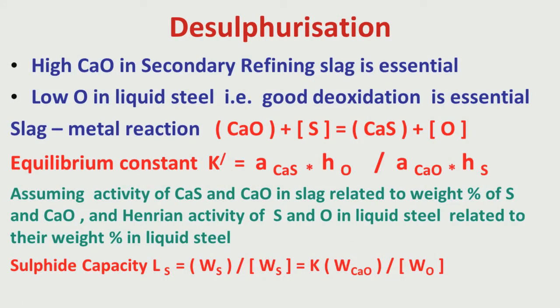Now, today let me talk about another important requirement called desulfurization. I have told you deoxidation is the first requirement for secondary refining. You have to first deoxidize the steel. That means the soluble oxygen level must be brought down, then only the subsequent reactions are really effective. I will come to why it is required. Initially there has to be deoxidation, then only the desulfurization reaction is effective.